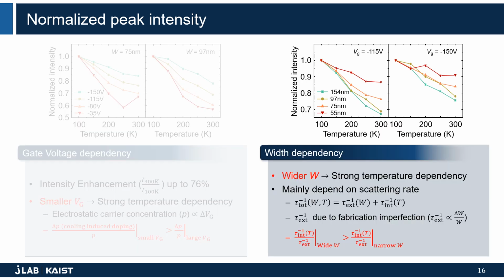Then let's see the width dependency. In order to isolate the additional doping effect, I compare the results of different width samples at high gate bias. That means the effect of temperature-induced doping becomes minimized. It can be seen that the temperature dependency gets stronger as the width of the resonators gets wider. That means the wider one shows a larger change in normalized intensity with temperature change. In this regime, the peak intensity variation is expected to mainly depend on the plasmon scattering rate.